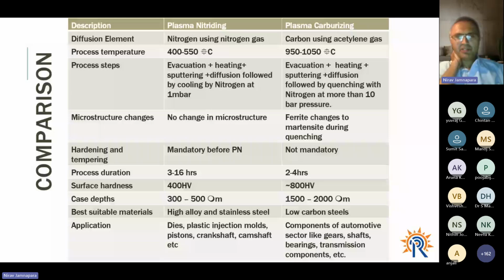Hardening and tempering is required before plasma nitriding, but is not mandatory for plasma carburizing. Process duration is higher in plasma nitriding, and it is lowest in plasma carburizing, because the hardness can be achieved in merely 2 to 4 hours. The case depths are much higher in plasma carburizing, and the applications of plasma carburizing are in gears, shafts, bearings, transmission components, etc.